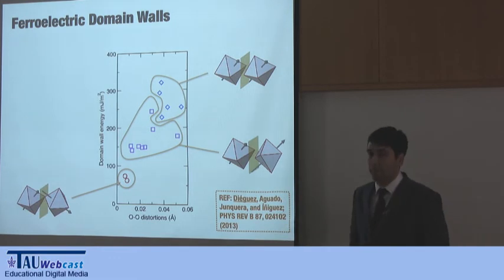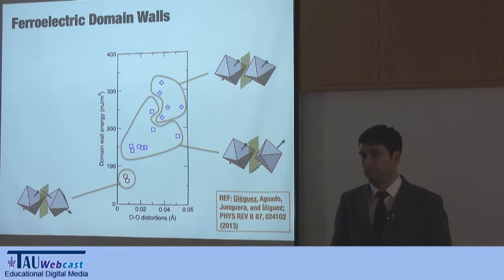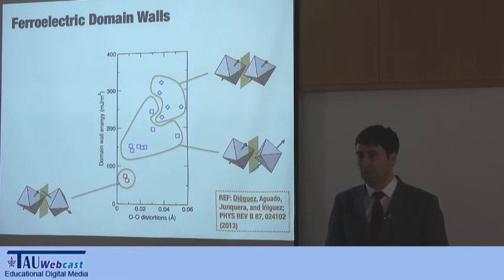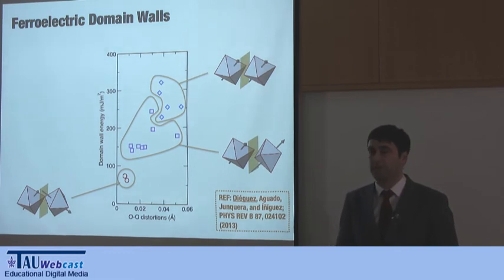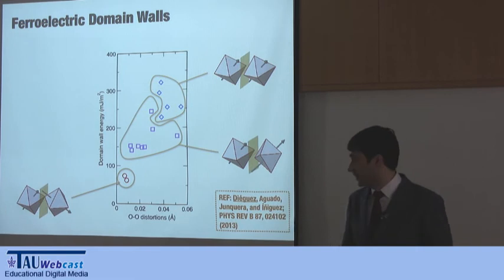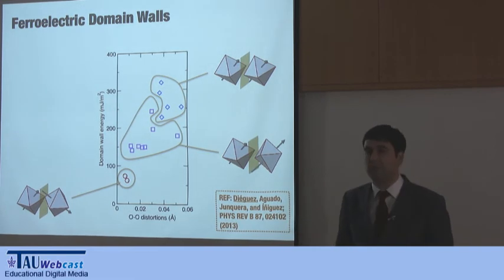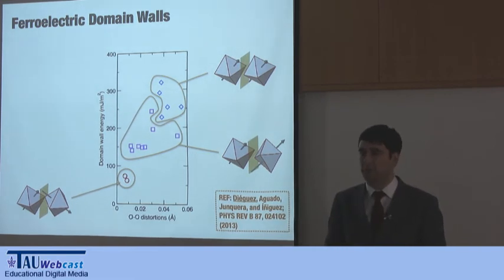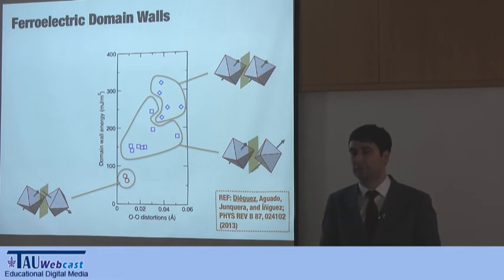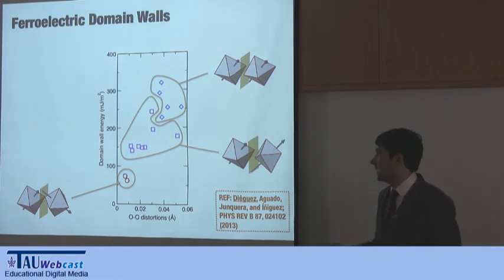This is zero temperature? This is zero temperature, yes. So the difference in energy is very small. The difference in energy is not that small. So fluctuations would not actually make any... This is our assumption. Because precisely bismuth ferrite is very stable until up to 800 degrees. So, and for example,